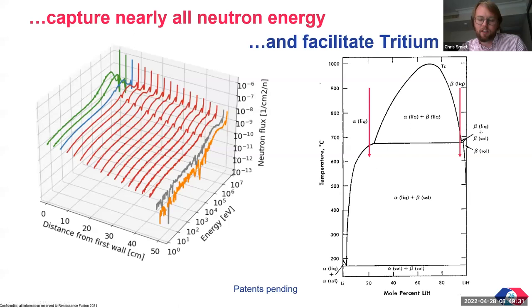And this is something we're investigating right now with a DOE INFUSE grant together with Savannah River: we're investigating if we can use the isotopic effect in the difference of mass between deuterium and hydrogen and tritium in order to, if we very accurately manage the temperature, targetedly precipitate the beta, the hydride-rich phase, but even targetedly precipitate the tritium and the deuterium separate from the hydride forms. And so facilitate the tritium extraction from the liquid metal, which also forms the working fluid.